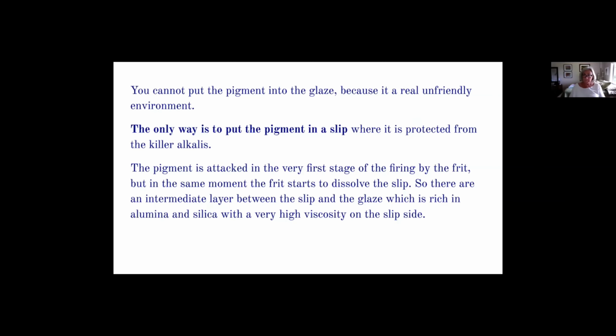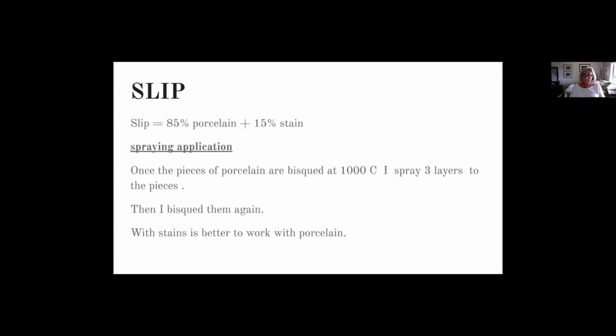The frit you use eats the cadmium. And as Jose said, you cannot put the pigment into the glaze because it's a really unfriendly environment. The only way is to put the pigment in the slip, where it is protected. The pigment is attacked, so to not lose the reds, you must apply 3 layers of the slip on the pieces. Here is the recipe for the slip: porcelain 85% and 15% stain.